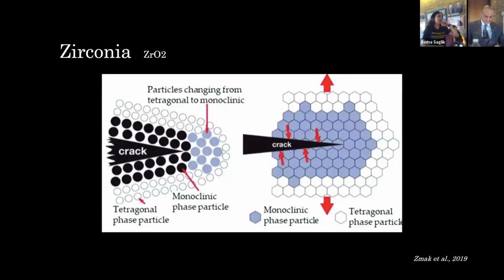And that gives us the understanding of the fracture toughening property of that material. If you see here in that diagram, with that zirconia which has been stabilized already, we have those white particles, which are in the tetragonal phase. Let's say this material was subjected to some sort of force over a long time, with, let's say, saliva, as it's being used inside the mouth, a crack might actually form. Those yttria particles have enough stored energy to make the tetragonal zirconia undergo phase transformation to monoclinic.